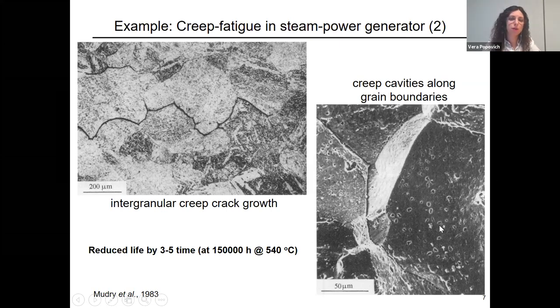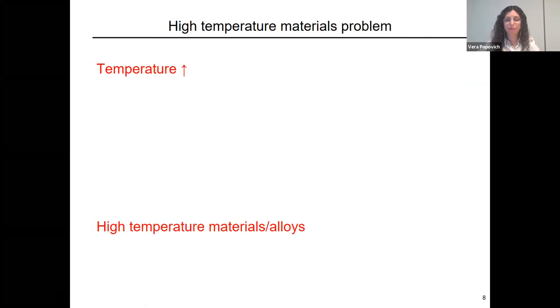We will look more during our creep lecture, if we have enough time, into what kind of fracture appearances you can have when you look inside the material. What is also important to note here is that compared to the virgin material, so the material that didn't experience this kind of prolonged exploitation, in this case about 17 years at 540 degrees C, the lifetime is reduced by 3 to 5 times. So that's to give you an order of magnitude of how these exploitation conditions can reduce the lifetime.